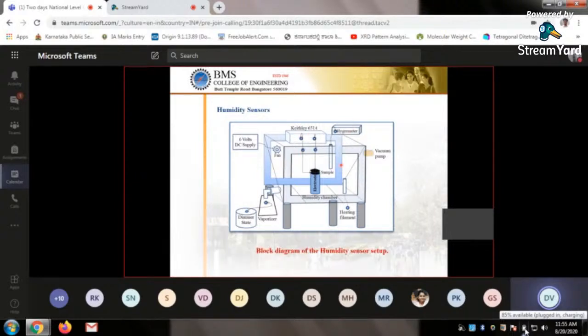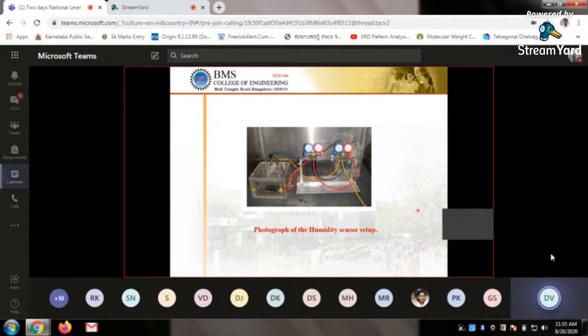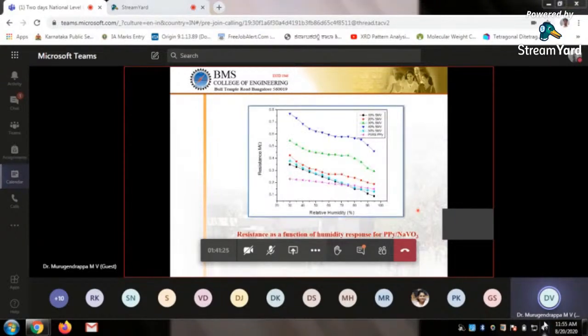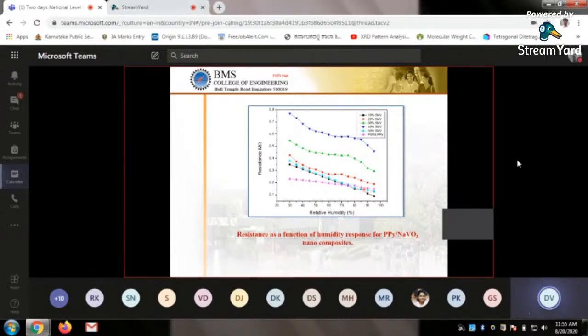We have a hygrometer to measure the humidity inside, and we have a thermostat at the vaporizer to increase the humidity inside the glass. A simple setup, and this is how it looks. It's an actual photograph of the simple humidity setup that we have set up in the lab. And what we observed: if you plot a graph of resistance and relative humidity, as humidity increases, resistance decreases. For anything to be a good sensor, it should be a linear variation. It may be increasing or it may be decreasing.